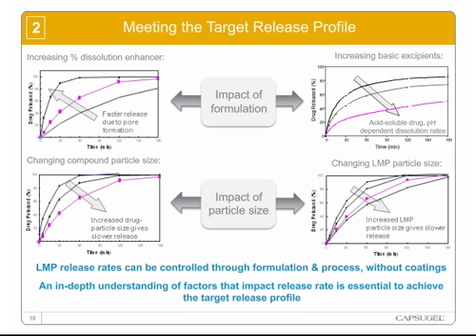The lower two panels speak to the capacity to modulate drug release rate by controlling particle size of LMP or the drug crystal size within the particle as well. In short, these dissolution results are critical to the overall understanding of the azithromycin LMP formulation, and were used to identify key formulation parameters that must be tightly controlled for consistent performance. In addition, these results also illustrate the capacity to effectively modulate the rate of drug release from LMP formulations without the use of external coatings.